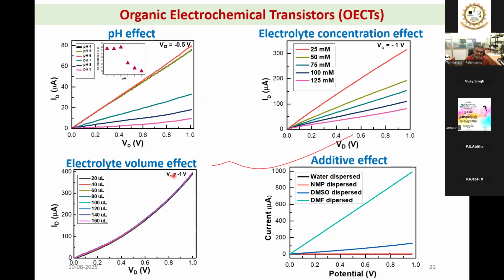On the other hand, this is a very important observation. The transistor works really consistently with different amounts of electrolyte or different amounts of sample. Starting from 20 microliters all the way up to 160 microliters, there is no change in IV characteristics. It means that even with 20 microliters, you can get the consistent result that you can get with 100 or 160 microliters.